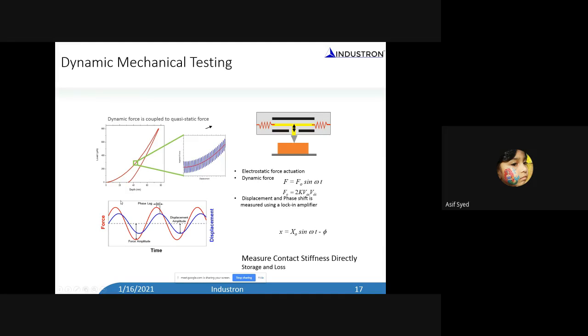They will be, the force and the displacement will totally overlap with each other. There won't be any phase shift. But if you do it on a viscoelastic material like polymers, you will see this phase shift. Actually, the displacement will lag behind the force. When you apply a force, it takes a little bit of time for the material to respond. So the displacement will lag behind the force, and if you measure this phase lag, you can calculate the loss component of this viscoelastic material.